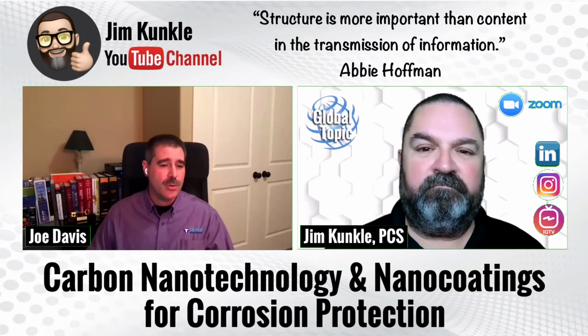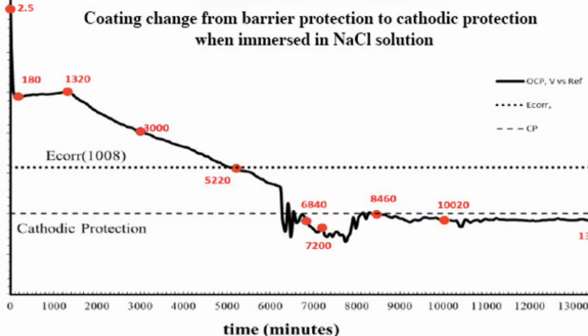And the picture that you're showing now shows an OCP, which is an open circuit potential, which you basically test the potential between 2 points of a cell. And as you see, as the electrolyte penetrates this film, about halfway through, it looks like someone turns a rectifier on. And that is because we've reached that potential for corrosion at the steel surface, and our zinc kicks in and it recognizes it and turns on, and you can see it carries that cathodic protection all the way to the end of this particular test.